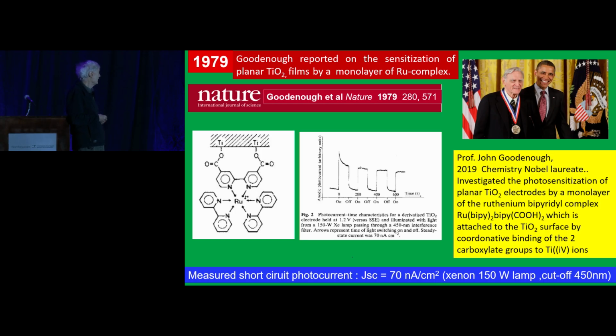However, the output of this device was very low, 70 nanoamps per square centimeter in equivalent sunlight, which is about 100,000 times less than what a silicon photovoltaic would produce. And so at that time, the prevailing opinion was that we shouldn't touch it. As a young scientist, I was told, don't go in this direction. It's a fruitless effort. No chance to get those numbers up by 5 orders of magnitude.